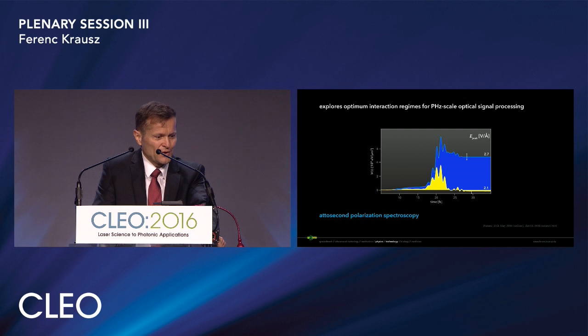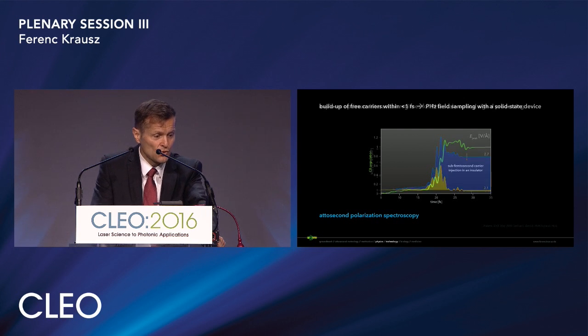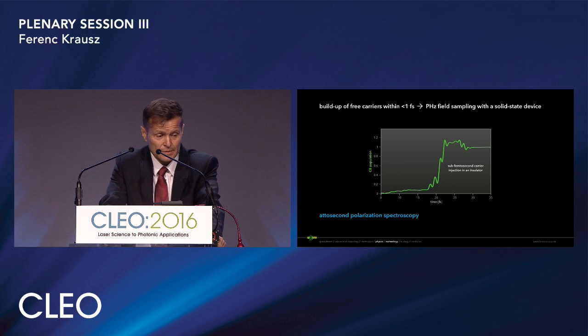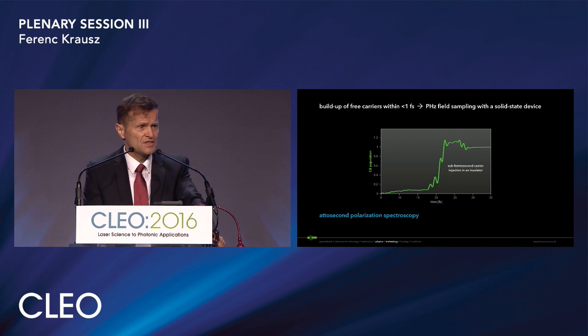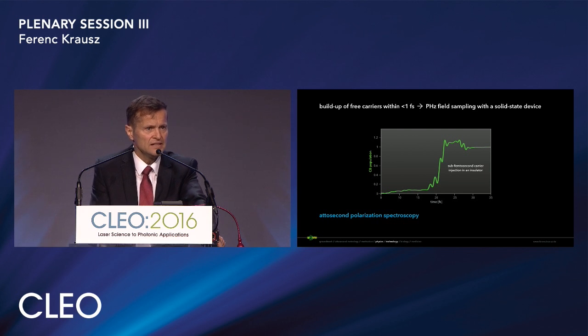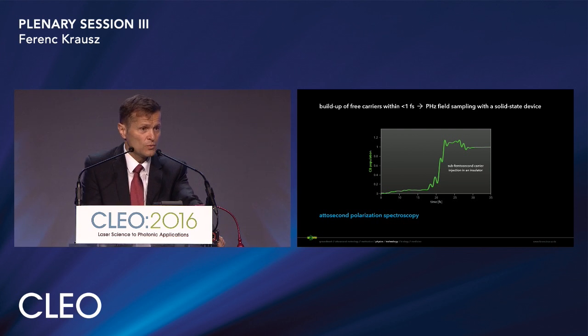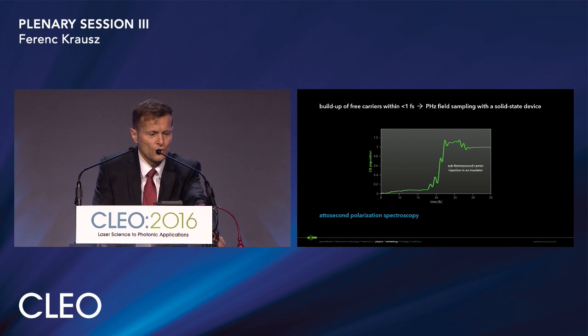Attosecond polarization spectroscopy will explore the optimum interaction regimes for petahertz scale optical signal processing. It has also revealed the buildup of free carriers in the conduction band of an insulator within less than 1 femtosecond near the highest field strength, which actually opens the door for optical field sampling up to petahertz frequencies with a solid-state device. This is something I'll come back to in a few moments.